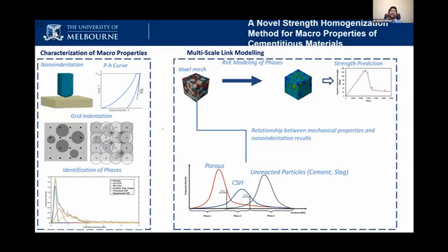Then I will explain this in summary, like what we have done here. We do the nano indentation like a grid. We do a 1000 by 1000 grid to get a better understanding of the sample. Then we get the result. Basically, we get the hardness of the indentation, and we plot it, and from a statistical analysis we divide that